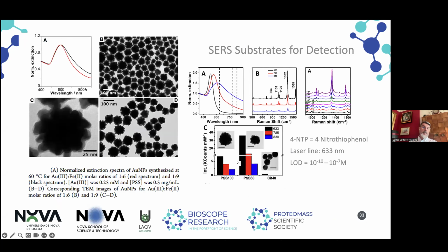In fact, these nanoparticles that were produced are actually being used as a SERS substrate for optical sensing. In this case, I show you just the detection of the 4-nitrothiophenol molecule. This nitrothiophenol molecule is attached to the surface of the nanoparticles. As you can see in the fingerprint of the SERS spectra, we can go down to a 10^-10 limit of detection, in which the spectra show the typical signals for that molecule.